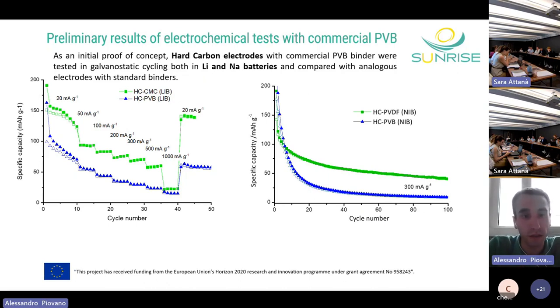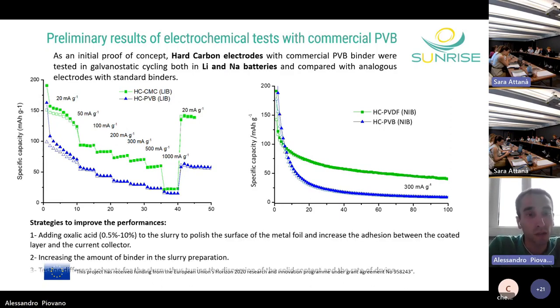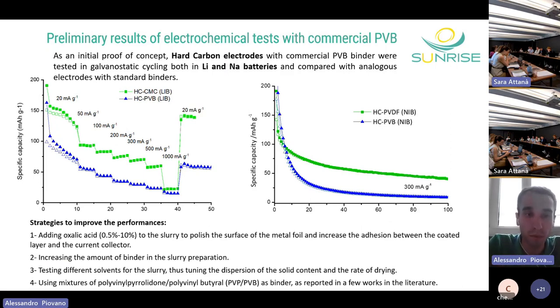batteries, stable towards many cycles, even at a very high current rate. But the performances are still a little bit lower with respect to standard binders. So some attempts to improve the performances are to add some oxalic acid in the slurry, which polishes the surface of the metal foil and increases the adhesion between the electrode and the current collector.